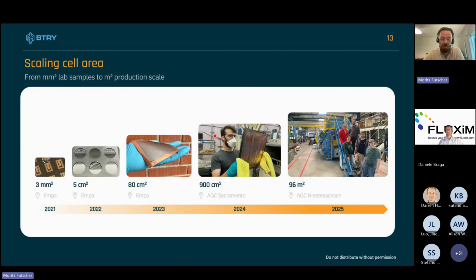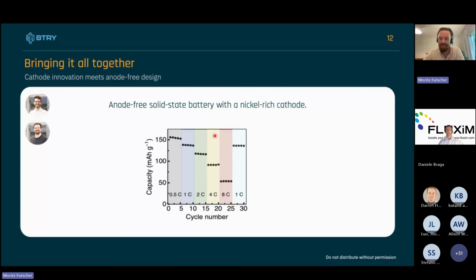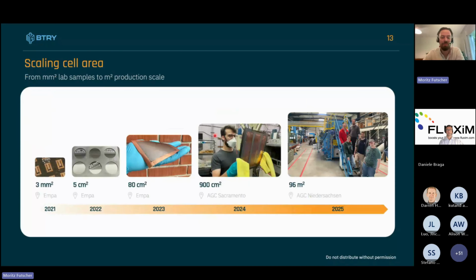And then from starting a company, there were many other challenges involved. One of them, for example, was scaling, because in research we usually work on very small areas. You see here one which is 3 millimeters squared. This is good enough for research and for understanding fundamentals of materials, but not enough for a product. So what we did is we scaled this area, and here we worked with a partner, which is Asahi Glass Company, which is one of the largest glass producers globally, and also produces these vacuum coating machines.